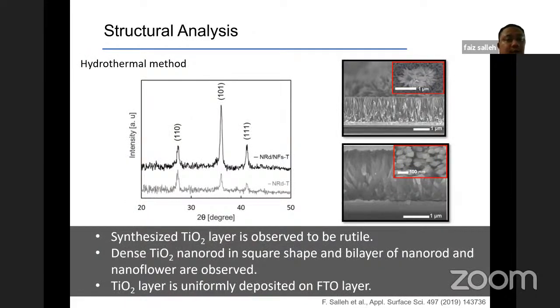So the first one is the hydrothermal method, where our collaborators managed to propose a technique to fabricate two kinds of layer. One is the bilayer, consisting of nanorod and nanoflower, and one is the single layer, consisting only of the nanorod structure of TiO2. By using the hydrothermal method at low temperature, the synthesized TiO2 layer is observed to be rutile, with the respective peaks at 110, 101, and 111. We can also observe that the dense TiO2 nanorods are square-shaped, and in the bilayer, we have two layers, the nanorod and also the nanoflower. This TiO2 layer is also observed to be uniformly deposited on the FTO glass substrate.